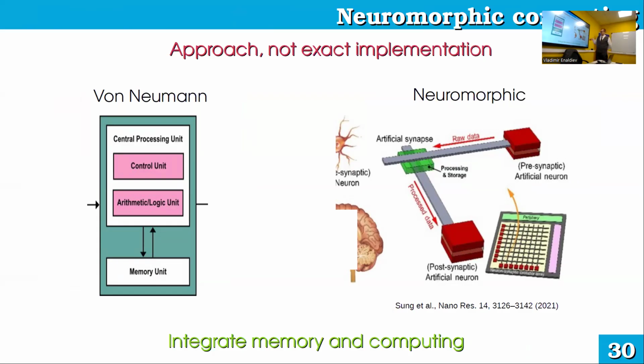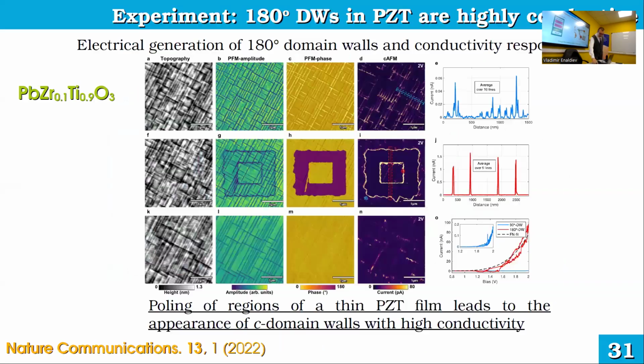All this neuromorphic stuff. Basically, the main idea of going from von Neumann architectures is to unite compute and storage operations. So your elements simultaneously can compute something and store some information. And here is an interesting case of PZT thin films. Upon repolarization of these films, the surface of the film is traced with conductivity traces. And the conductivity is pretty good. Actually, it's nanoamperes.